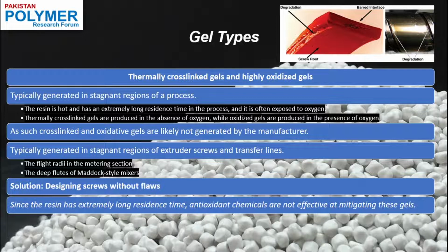The flight radii in the metering section of the screw should be relatively large to the local channel depth, because if the radii are small, eddies can occur. These eddies are called Moffatt eddies, and they can create regions with long residence times. These regions can act as a location where the resin can degrade because of staying for a longer period of time. The sharp corners are the places where these Moffatt eddies are created as secondary flows. A simple process upset can knock the degradation off of the flights and into the main flow, which will eventually create defects in the film product.